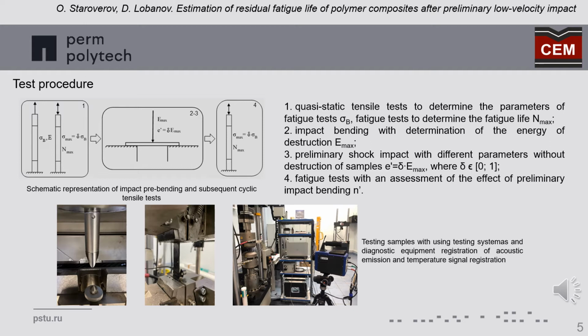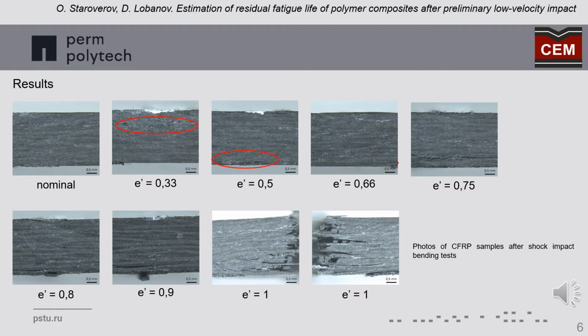From experiments of impact bending, the potential energy Emax was determined, at which the samples were destroyed. Further tests with preliminary impact according to the 3-point bending scheme were carried out in the range from 0.3 to 0.9 of the destruction energy E. Single blows were made across the entire width of the samples. A visual inspection of the samples was carried out.